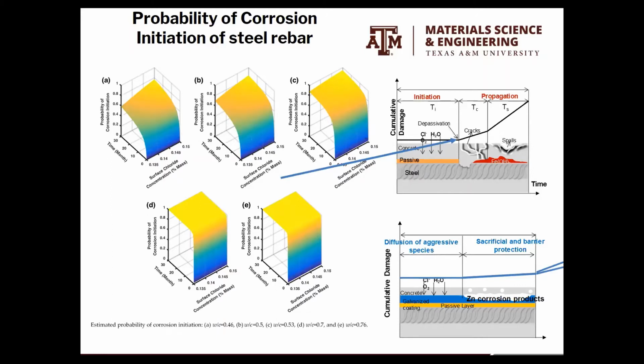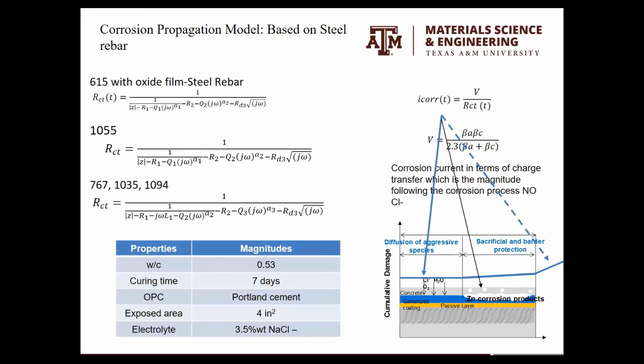But we are building the same model, because now we have the deterministic part, and you see that's the classical on the top. In the bottom, now we can see in terms of probability, and based on what we did, the modeling for each one of the rebars. This is our model. Now we can set the corrosion rate based on the characteristics of the rebar and the characteristics of the signal that we got in the lab. And we can extrapolate this equipment and this methodology into the field, all right?